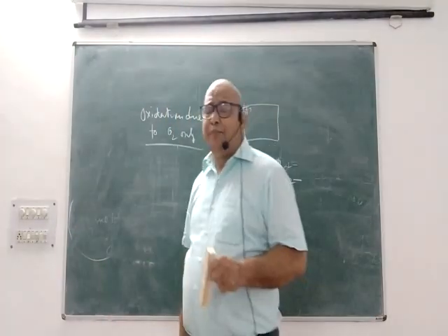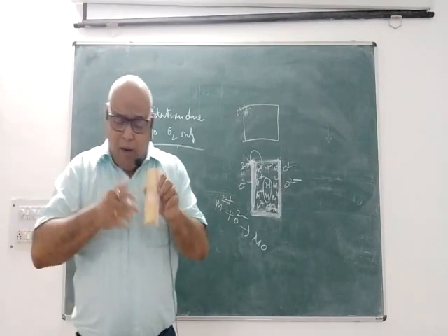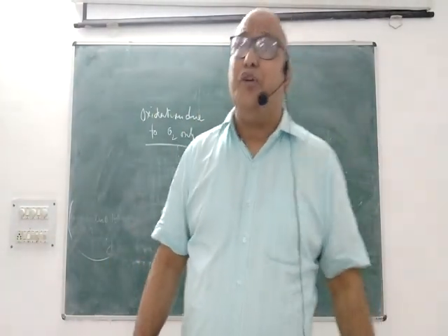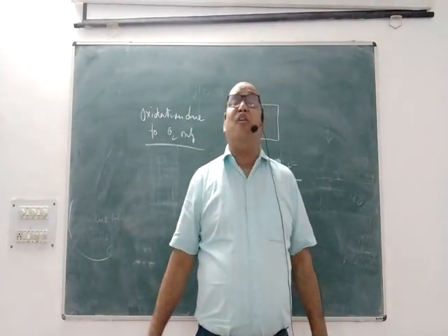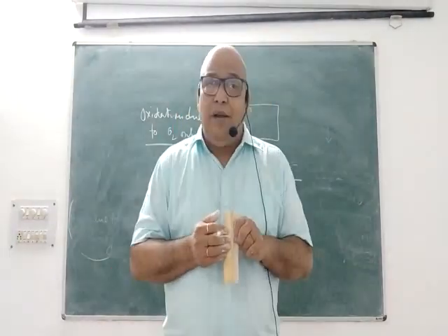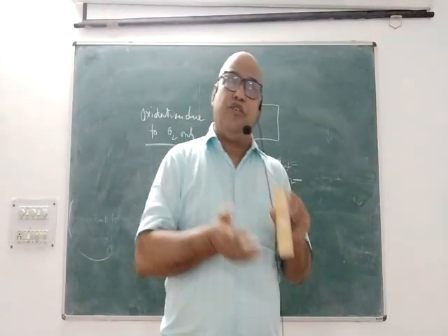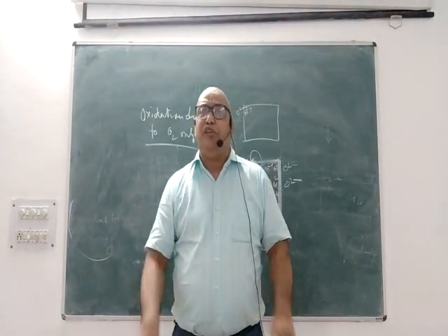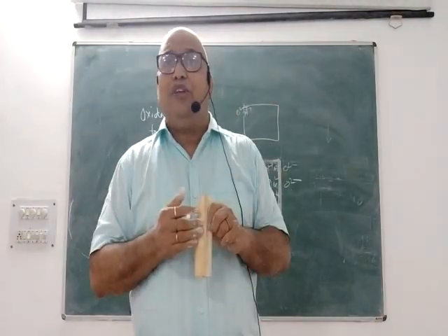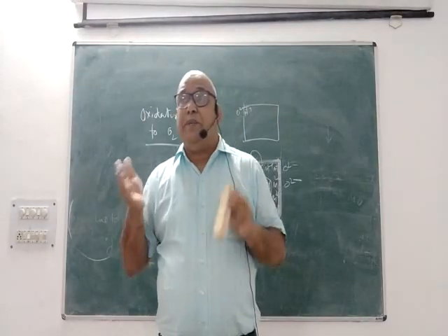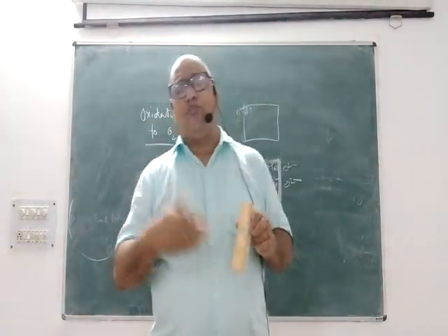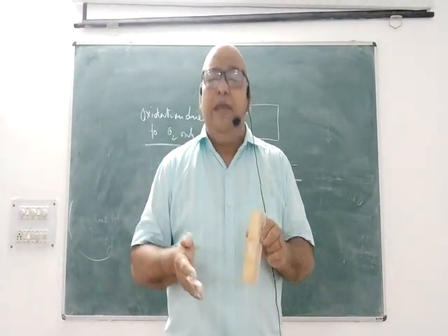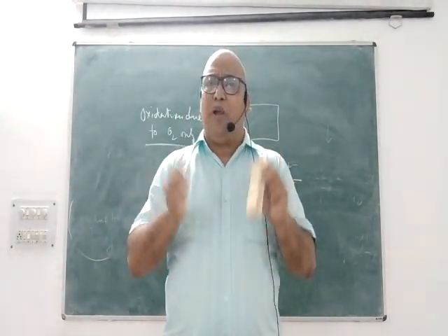Now both M2+ and O2-, being very close to the surface, will interact, and during this process oxide layer will be produced. Once oxide layer is formed, the interaction between metal ion and oxygen ion will be restricted. In that situation, if they want to react, there will be two possibilities. Either metal ion has to come out or oxygen ion has to go in. In fact, both are possible, but here metal ion will come out because of smaller size of cation.